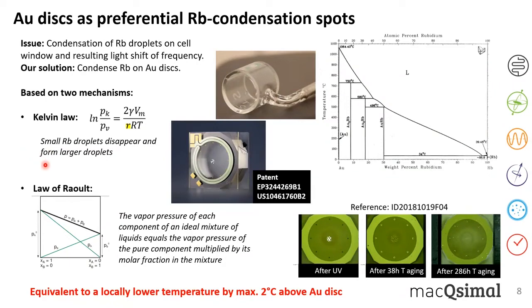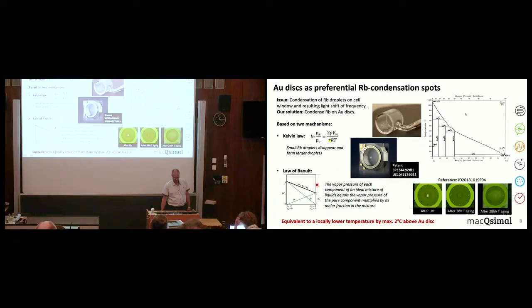And on the other side, we have the law of Raoult, which says that the vapor pressure of each component of an ideal mixture of liquids equals the vapor pressure of the pure component multiplied by its molar fraction in the mixture, which means here, if we have rubidium on one side and gold on the other side, and we look at the vapor pressure, the rubidium has a vapor pressure which is quite important at the temperature of operation, but gold has no vapor pressure. So gold will not evaporate, as you all know by experience. So if we have any mixture of rubidium and gold, the vapor pressure above this mixture will be lower compared to the pure rubidium itself. And you see here quite well how this works.